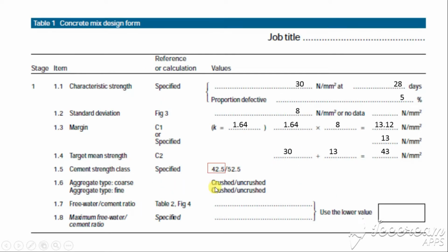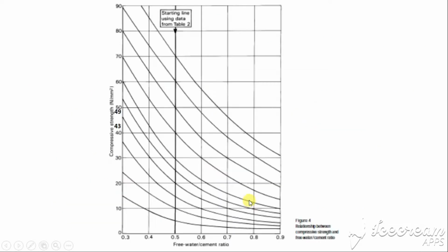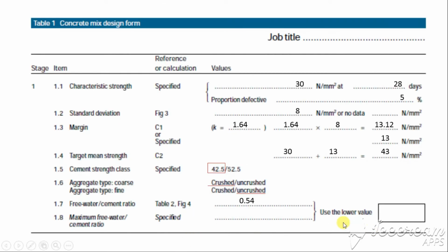For the type of coarse aggregate, we use crushed, and for the fine, we use uncrushed because we use river sand. For the free water cement ratio, we will refer to table 2 and figure 4. We will get 0.54. Here we got 0.54. Use the value from table 2, 49. Project to the 0.5 line, and then create the new curve, and then use the target mean strength 43. Project to the new curve and project to the x axis, you will get the water cement ratio 0.54. Use this value for our water cement ratio.